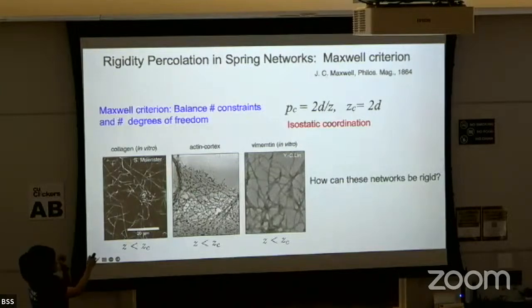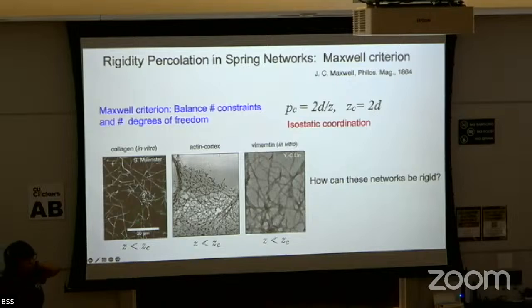This is also less than 4. So then you can ask, how can these networks be rigid, right? I showed you that for these networks to be rigid, Z has to be greater than ZC, right? The coordination. But these coordination numbers are all less than 4, and in this case, less than 6. This is a 3D thing. And experimentally, people measured the rigidity and shear modulus of these networks and find a finite value. So what are we missing?